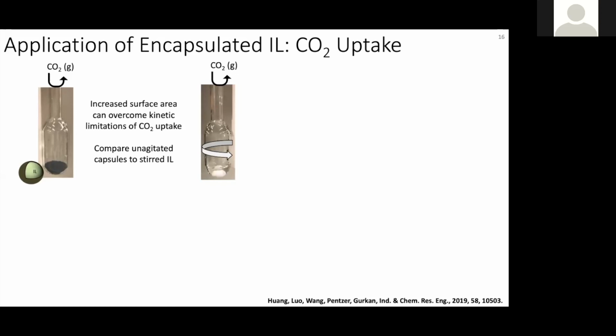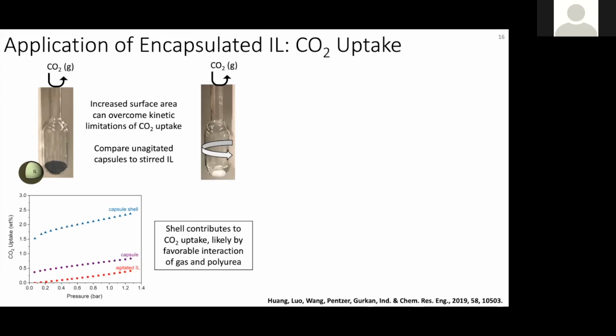So we envision that, again, provided our polymer shell was permeable to the CO2, we would be able to have the capsules unagitated and make use of the ionic liquid on the inside for CO2 uptake. And this is just a generic ionic liquid, I should say. And so if we look at the uptake capacity for the shell by itself versus the capsule versus the agitated ionic liquid, we actually see our capsule shell is really good at uptaking carbon dioxide.